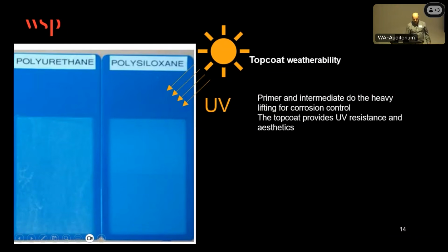The Australian standards present various long life coating systems, including polyurethanes and polysiloxanes. And they're typically expected to provide at least a 25-year service life to first maintenance, according to the codes. And while it's possible to extend these service lives for maybe up to 40 years or more, this is very much dependent on the film thickness, the exposure, and there's been a lot of testing that shows that some of these systems can be failing in as little as 15 years under very aggressive conditions.